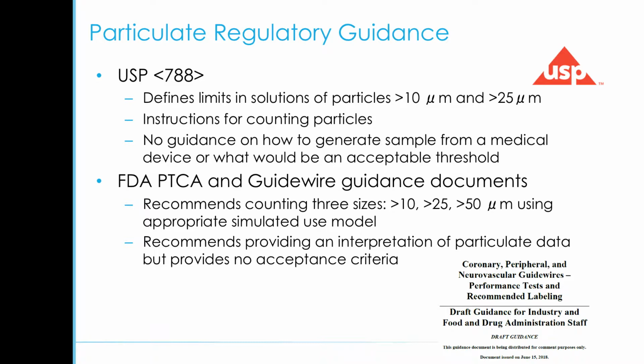FDA has put out several guidance documents, one for PTCA catheters, another one for guide wires, where they recommend counting not only in 2 different size bins, but 3: greater than 10 micron, greater than 25, and even greater than 50 micron, using an appropriate simulated use model. That simulated use model is up to the manufacturer's discretion to choose a relevant one. They also recommend providing an interpretation of the particulate data. The challenge is they don't really provide what exactly the acceptance criteria is for that.